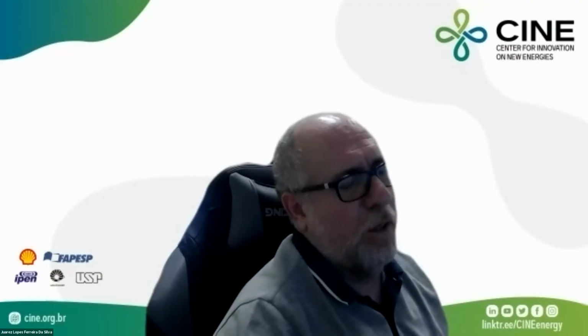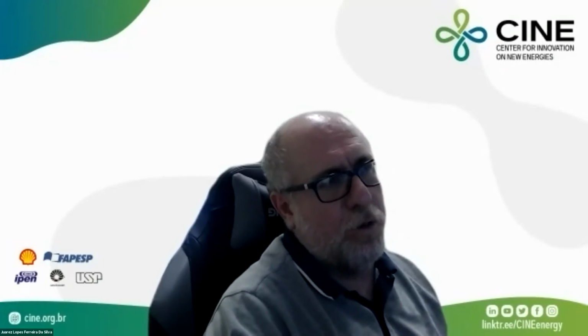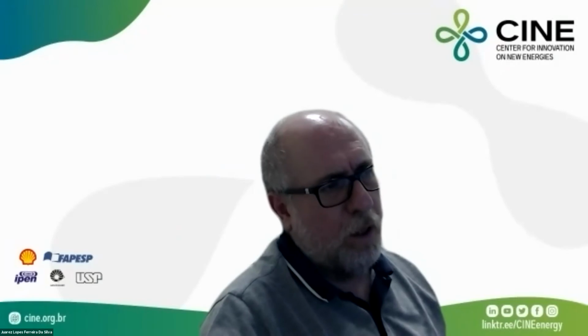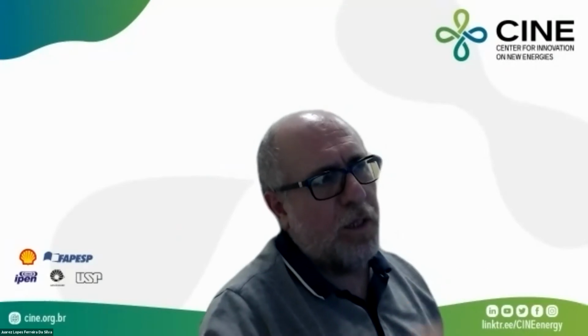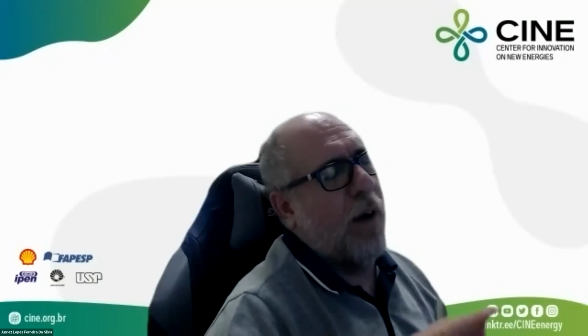Why I'm asking, Fabiane, is if you know the oxygen concentration on the samples, and you know the composition of the La2O3 and CeO2, then you are able to establish how many Ceria change the oxidation state from 4+ to 3+. For every oxygen that is missing in your sample, 2 Ceria change the oxidation state. Okay. Then the big problem is, like Fabio says, the following: once you have the oxygen composition, where are the Ceria 3+ located?